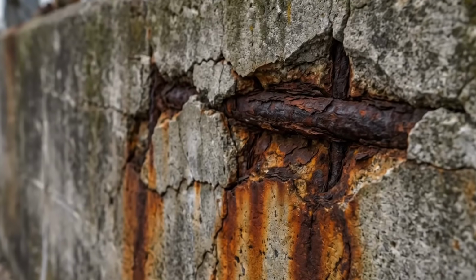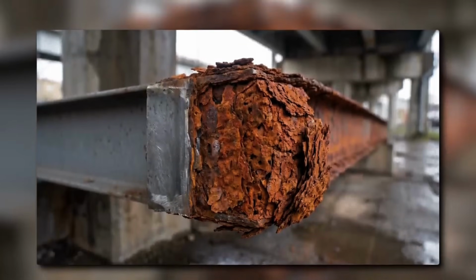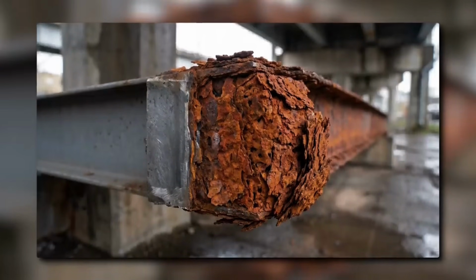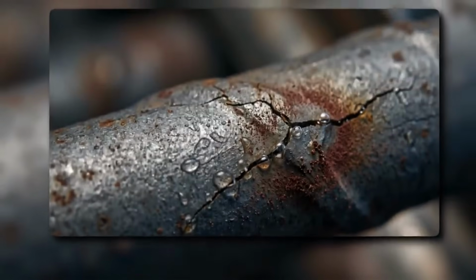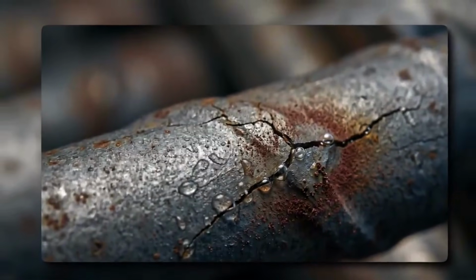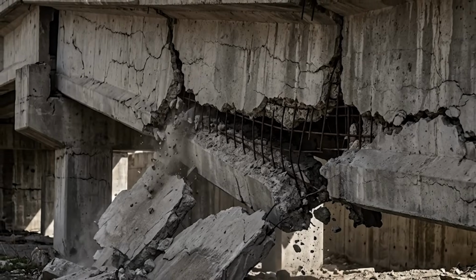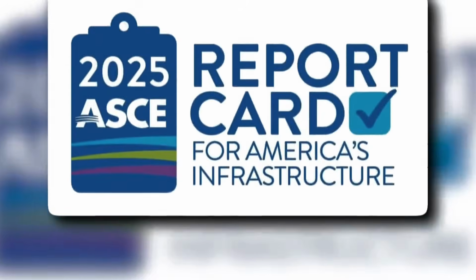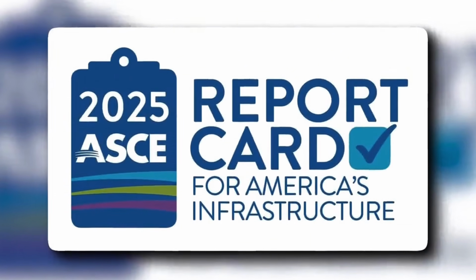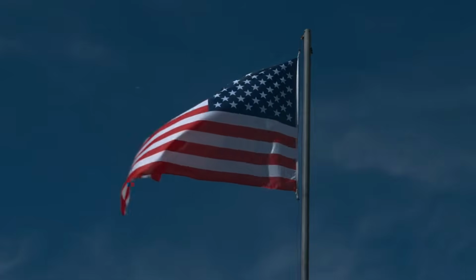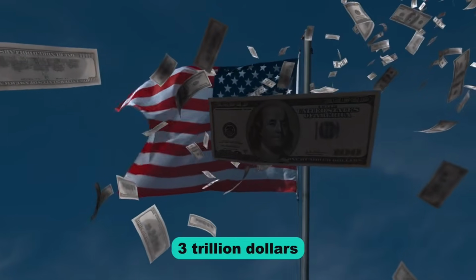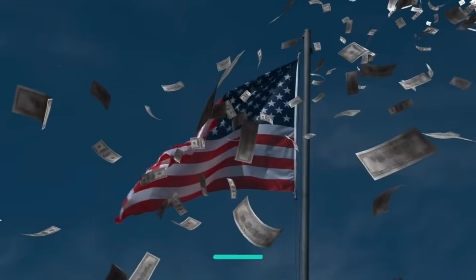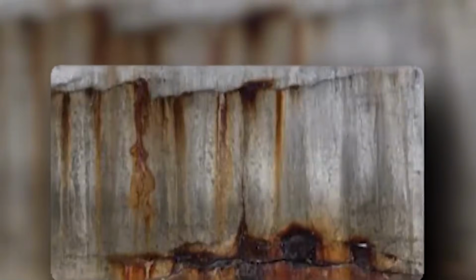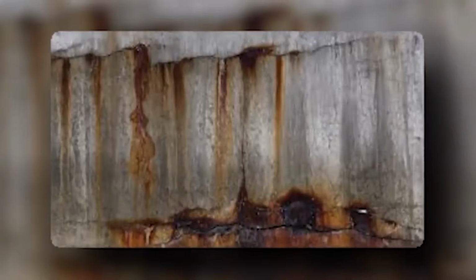Steel rebar has one fatal property: it rusts. The rust occupies up to 7 times the volume of the original steel. That is not a typo, by the way. When water and oxygen reach the bar through hairline cracks, the bar swells, the concrete cracks open further, and the structure fails. The American Society of Civil Engineers, in its 2025 infrastructure report card, estimated that the United States faces more than $3 trillion in unfunded infrastructure repairs by 2033. That is the kind of number that makes accountants cry. The single largest contributor is corroding rebar.